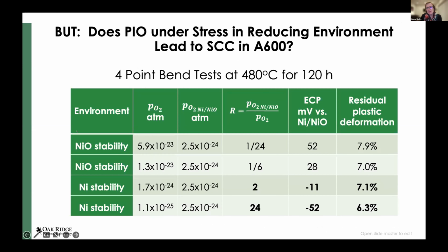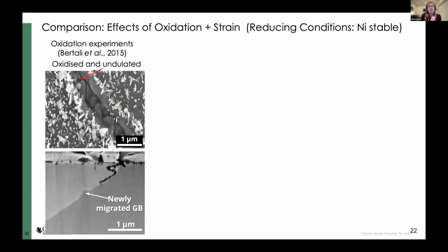Well, so we've got that preferential intergranular oxidation, but does it lead to stress corrosion cracking in the susceptible environments, which happen to be reducing environments? Will it lead to stress corrosion cracking? So some very lovely work by Liberato Volpe in terms of looking at 4-point bend tests in either oxidizing or reducing conditions in the environment of interest.